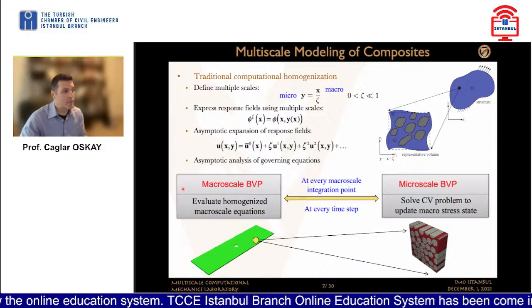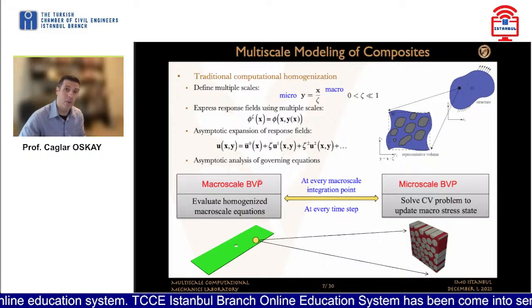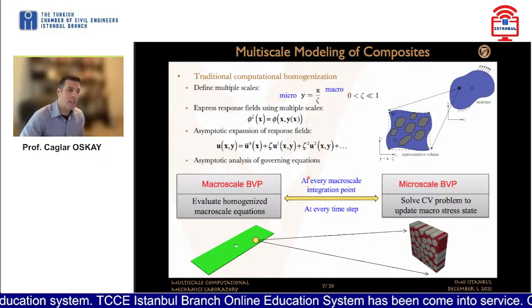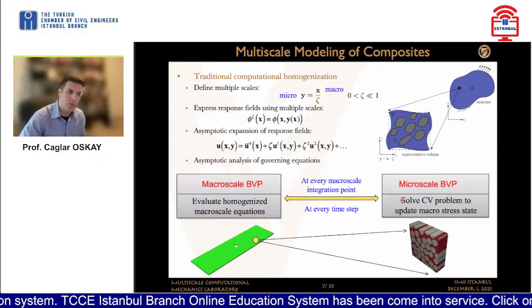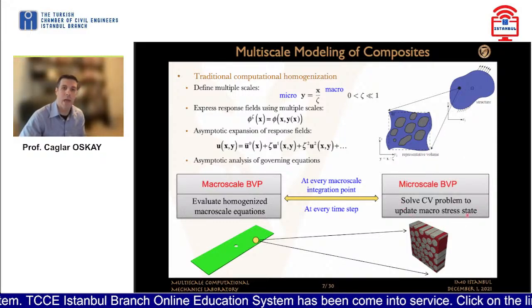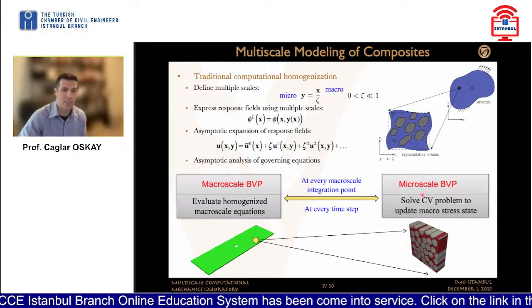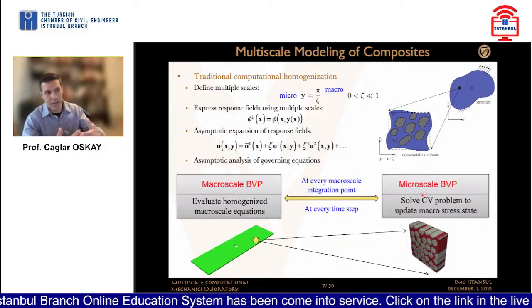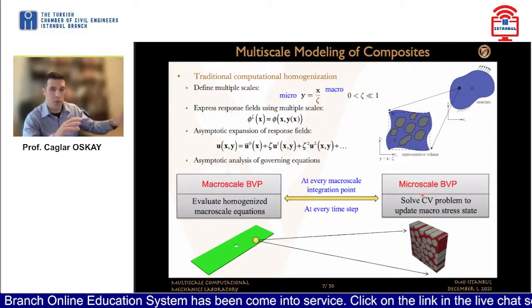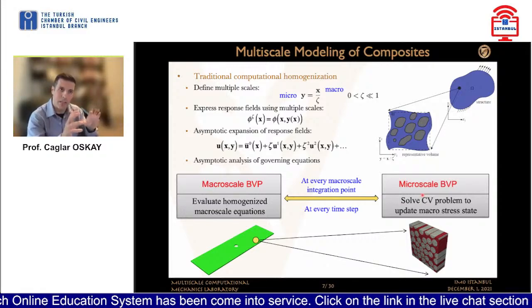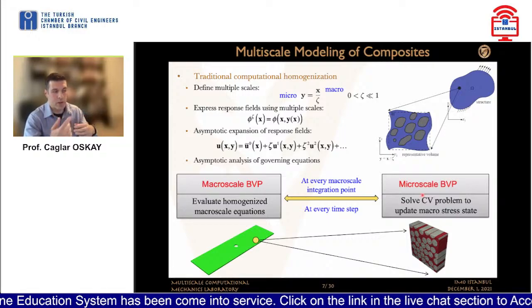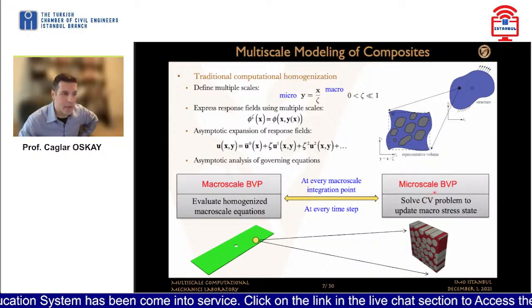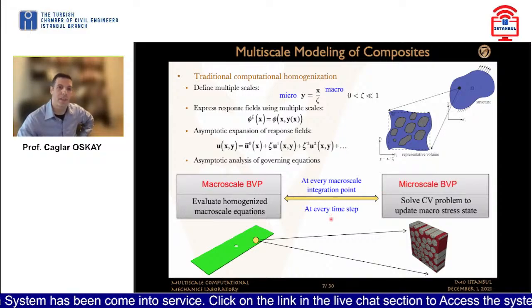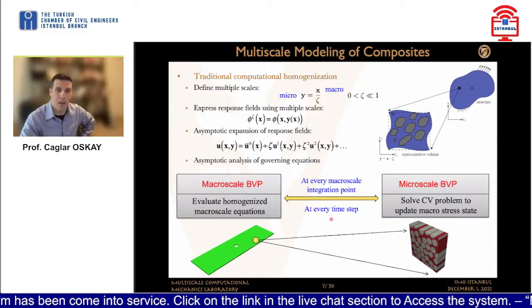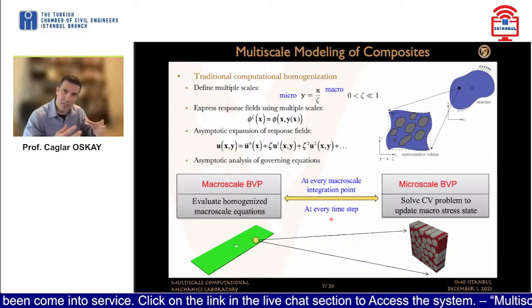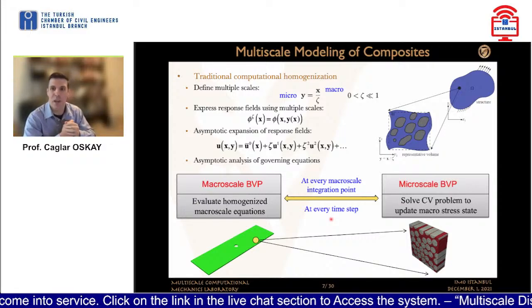And what happens is that the macroscale boundary value problem evaluates the overall response fields, and it communicates with the solution of the microscale boundary value problem to update the macroscopic stress state. So in this nonlinear analysis, one has to solve two nonlinear problems that are hierarchically coupled at the macroscale and the microscale. So you need to evaluate the microscale boundary value problem at each integration point at every increment of the macroscopic analysis. So it's a very computationally complex problem, is what I'm trying to say.